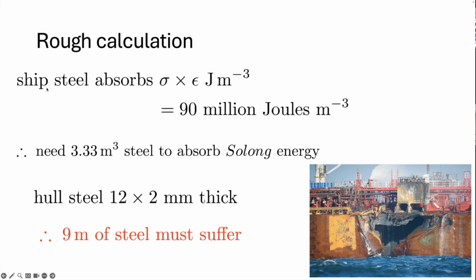So the ship steel absorbs stress times the plastic strain joules per meter cubed. So if I take the typical strength of a ship steel, around 300 megapascals, and its fracture strain, then the steel here is able to absorb 90 million joules per cubic meter of steel. Now, of course, we are not dealing with a cubic meter of steel, so I have to convert it into an area corresponding to the plates used for making this ship. So we need 3.3 cubic meters of steel to absorb the energy of the impact.